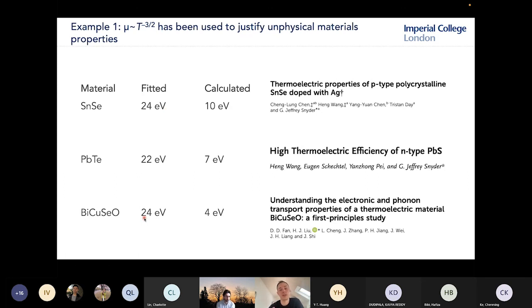More recently, people have gone on to calculate these materials in more detail and have found that in each case, they're actually dominated by polar optical phonon scattering. And when you calculate their deformation potentials, they're much smaller, in some cases almost an order of magnitude smaller. When you consider that deformation potential scattering goes as the deformation potential squared, you can really see that you're getting a very incorrect understanding of transport in your material. The second side of this is that the underlying mechanism of scattering controls the optimal temperature and carrier concentration needed to maximize thermoelectric performance. So if you're getting an incorrect picture of the scattering and you're basing your optimization efforts on that picture, it's going to be very difficult to optimize the performance to the ideal value.